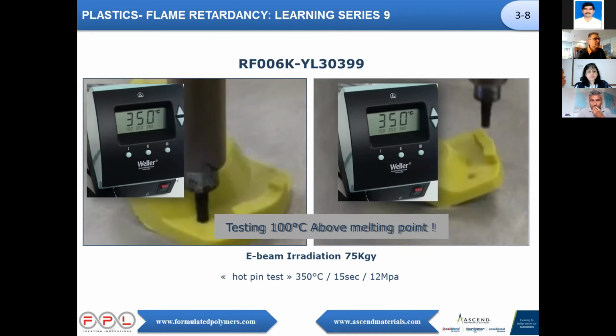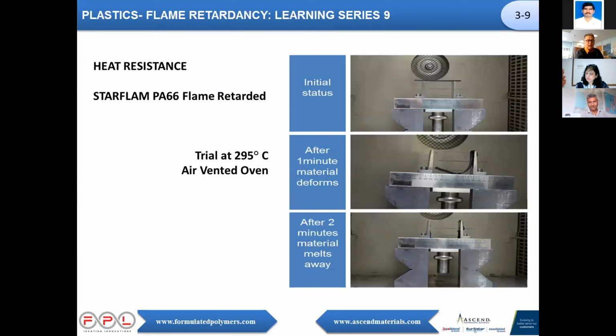So this is a kind of part in, I cannot disclose too much, but let's say an iron, and this part was in thermoset, and they could replace it due to this high heat short-term capability. And then you see the part, after a test at 350 degrees C, you can see that here also you can only see a small mark on this part. So this is an industrial part on stream, and maybe you will see this small part in Miguel's presentation in a bag. So just to see that it's really high volumes, and it's important because today customers still have an impression that it's an exotic application process. It's no more an exotic process, and everybody is using it not only in appliance but also in automotive now.